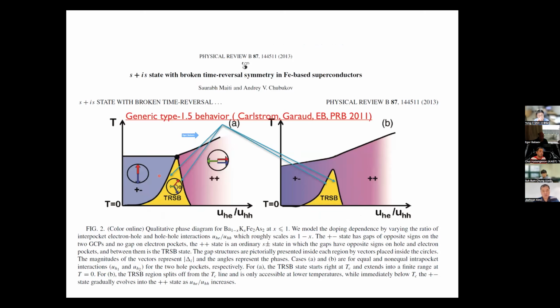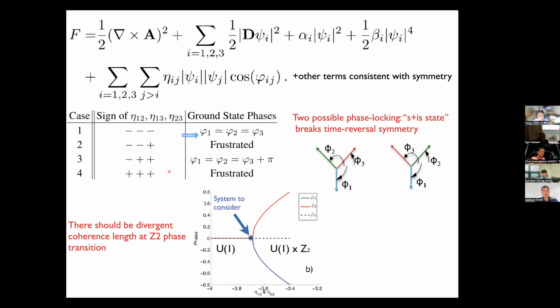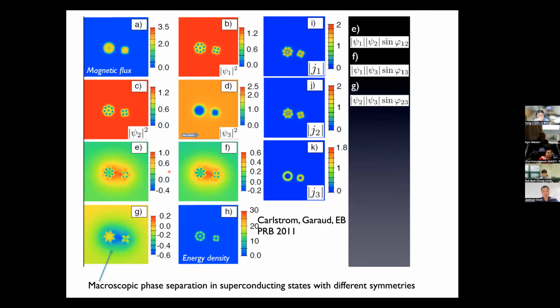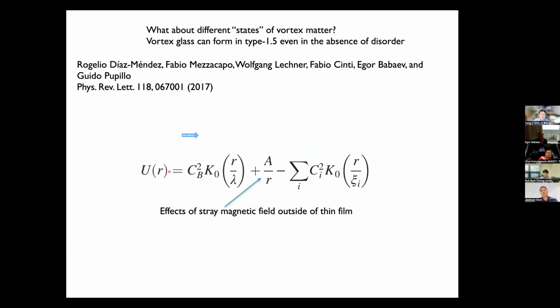So basically, it can be calculated that if you break time reversal symmetry in an S plus iS superconductor, you also have divergent coherence lengths at this phase transition, and then you also form vortex clusters. So near this transition, the type 1, type 2 dichotomy doesn't work.